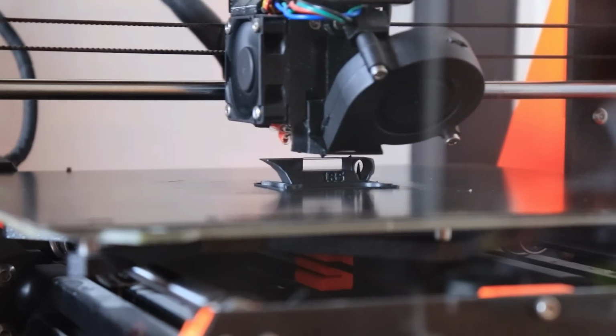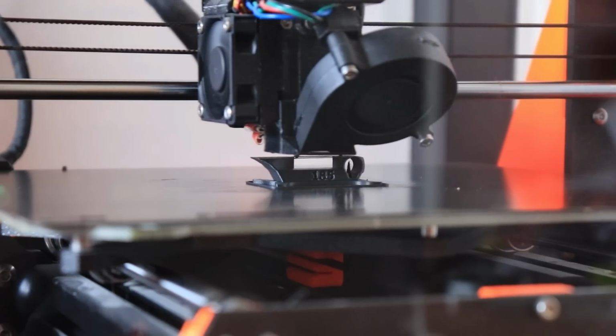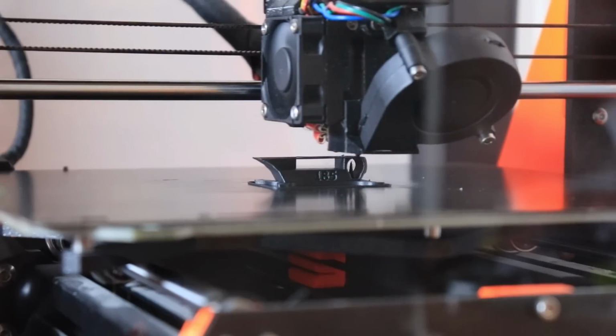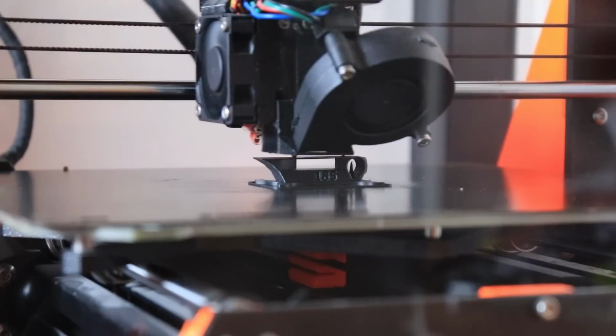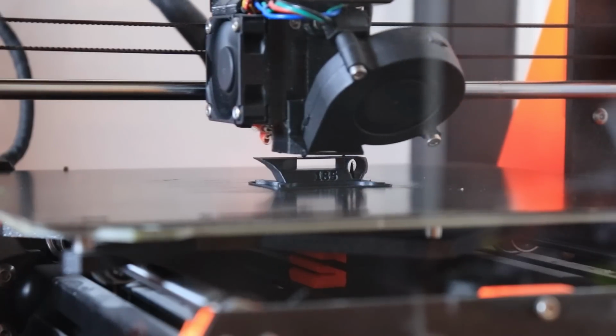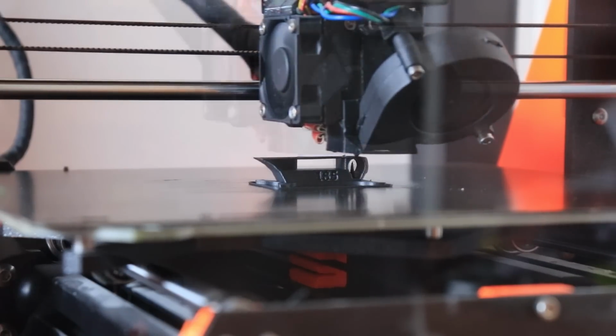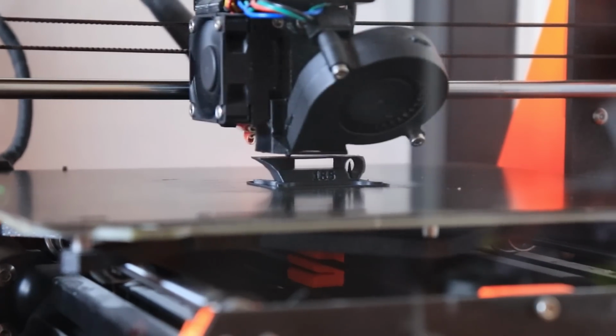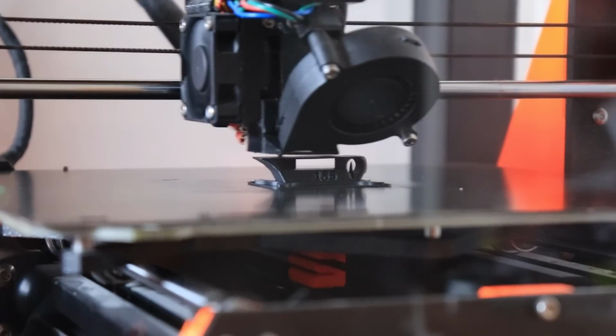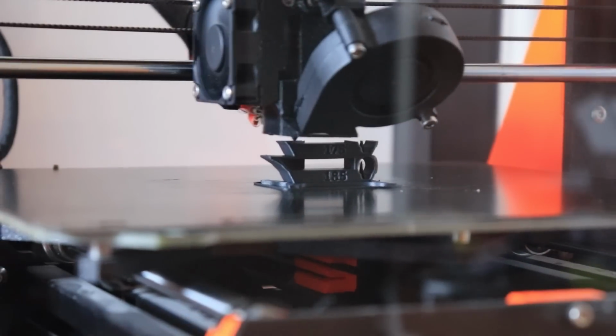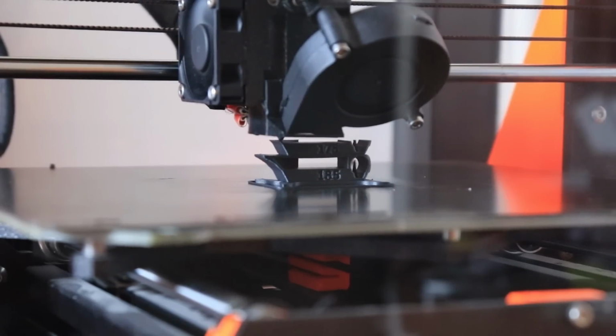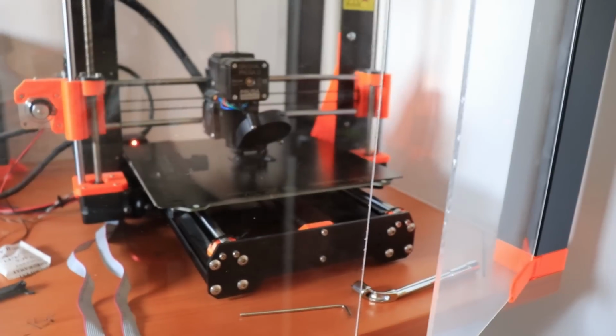And this is the bridging moment. The fan is on and I can see the temperature go down to 278 for the moment, and then goes up to 290 before it stabilizes again. And this is the last element on 275 degrees Celsius, and it looks okay so far. The printing is almost finished.